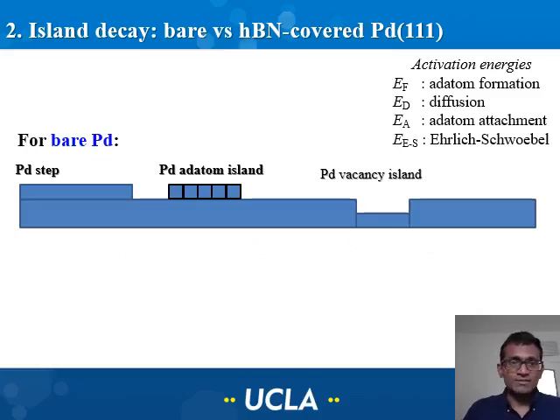And to explain this, here is a schematic. So for an atom island or for a vacancy island to disappear, there are a few processes involved. One, the atoms have to detach from the existing island, and this requires a barrier, and that is the adatom formation energy, and it has to diffuse on the surface. There is a barrier associated with it, the diffusion barrier, and if there is an attachment barrier, then that also plays into the rates of this island decay.